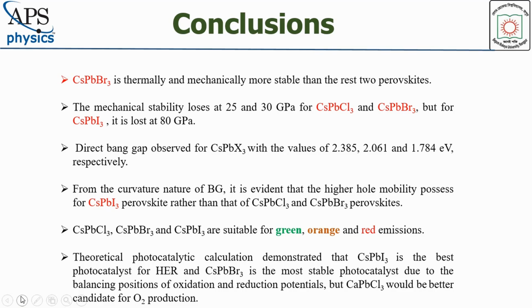Cesium lead chloride, bromide and iodide are suitable for green, orange and red emissions respectively. Theoretical photocatalytic calculation demonstrated that cesium lead iodide is best performer for hydrogen production. Cesium lead bromide is most stable photocatalyst due to the balancing position of oxidation and reduction potential, but cesium lead chloride would be a better candidate for oxygen production.